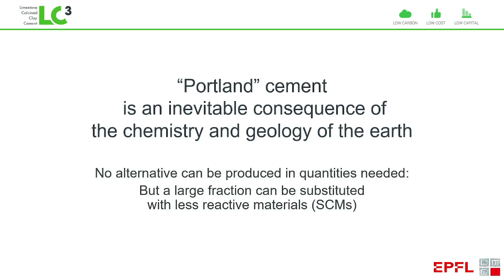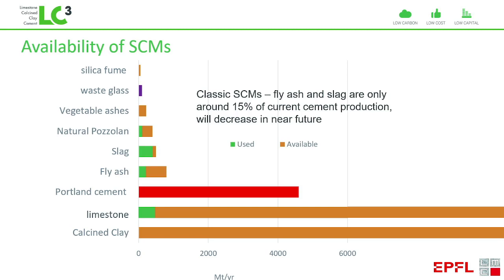But we can replace a large fraction of this Portland cement by other materials. And this has been done very successfully over a few decades now. But the issue is that the materials we are commonly using as replacements, which are what are called slag and fly ash, you see in the middle here, the amounts available are really quite limited compared to the demand for Portland cement. And these materials, the amounts will decrease in the future because they're coming from very CO2 intensive industries.